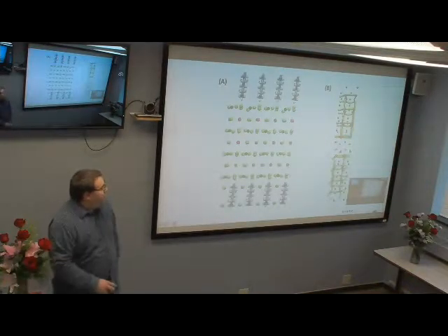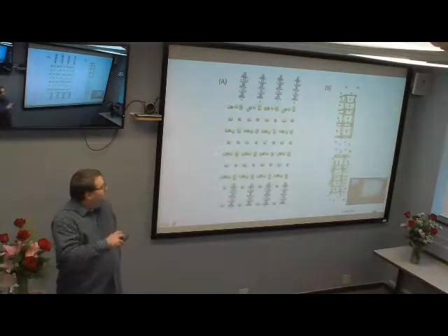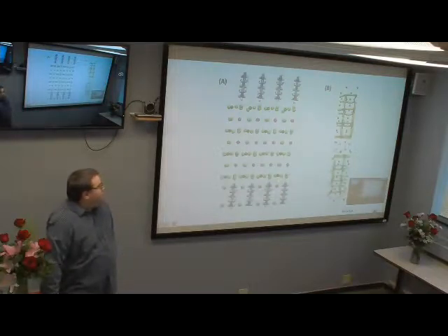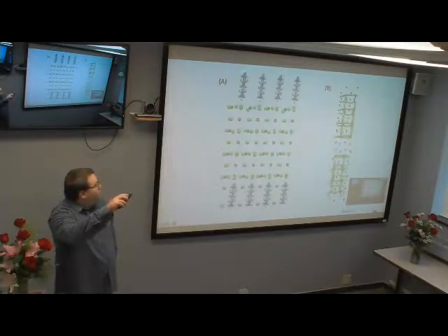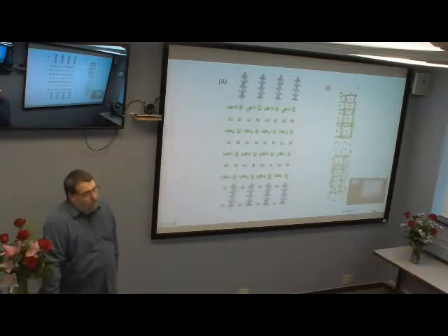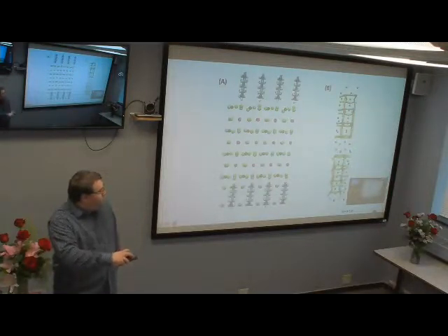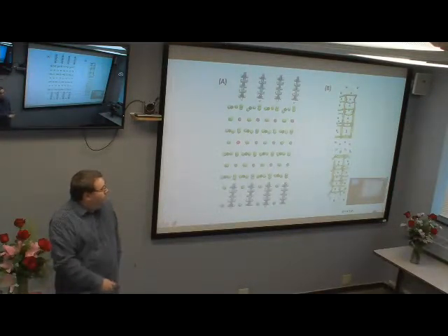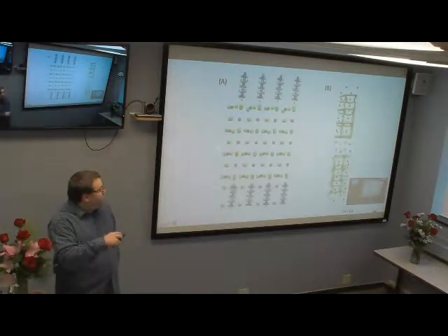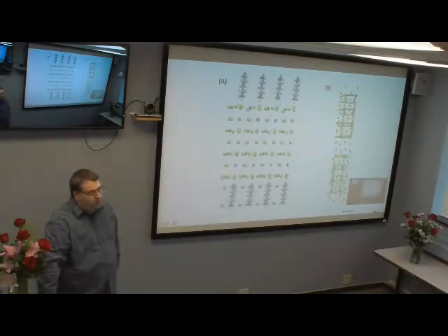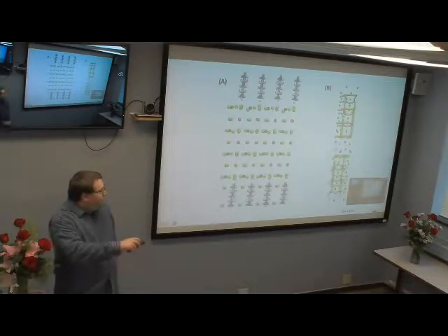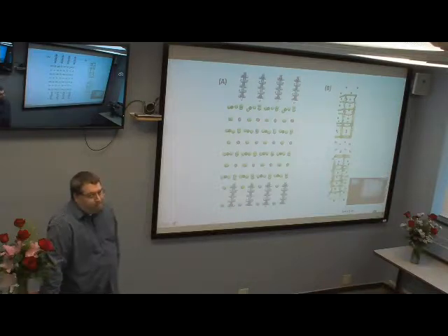So here you have the 2 models I was looking at. On the left, you have the hybrid Ruddlesden-Popper perovskite, and the organic ligand I was using to separate it was propyl-1,3-diammonium. And over here you have the Ruddlesden-Popper phase perovskite. The perovskites themselves, which are these structures, are cesium lead chloride, but the halide that was used to separate them is iodine.